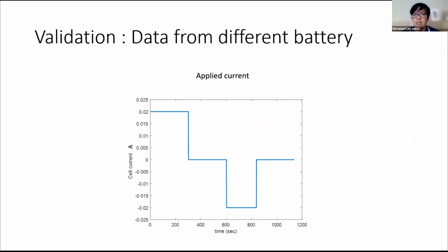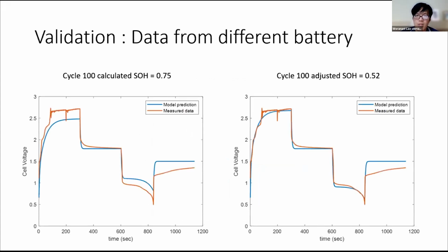The next validation test is data from a different battery. This data comes from the response of a charge-discharge cycle, so it includes charge and discharge in one plot. The plot shown in this slide is the applied current profile. At cycle 100, prediction with the calculated state of health of 0.75 shows some error, while adjusting the state of health to 0.52 was able to reduce the error.